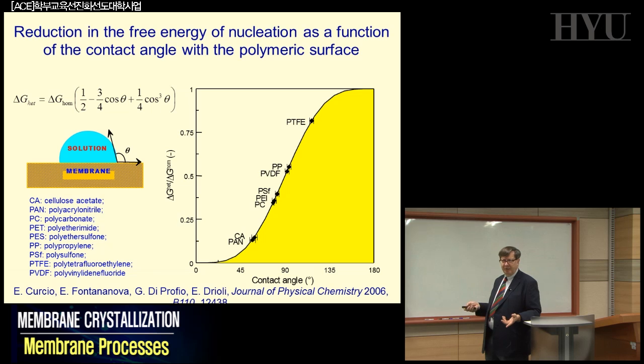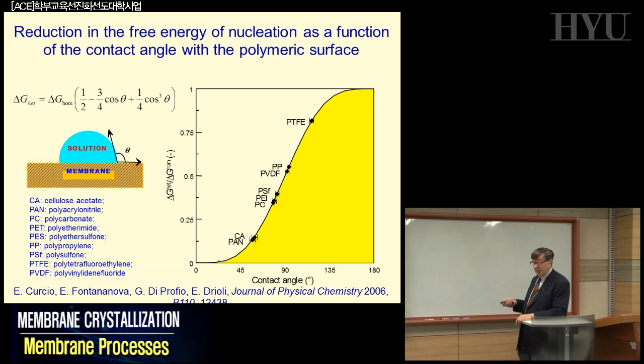And so we said, what is happening? In the literature, we expect to have crystallization in 3 days, in 1 week, 6 months in some cases, and we have it in a few hours or a few days. So we started to try to understand, and it came out that the results were correct.